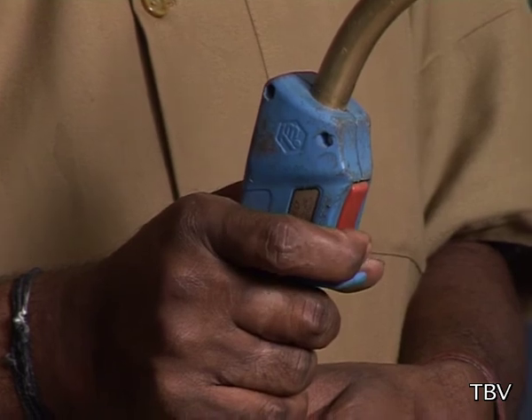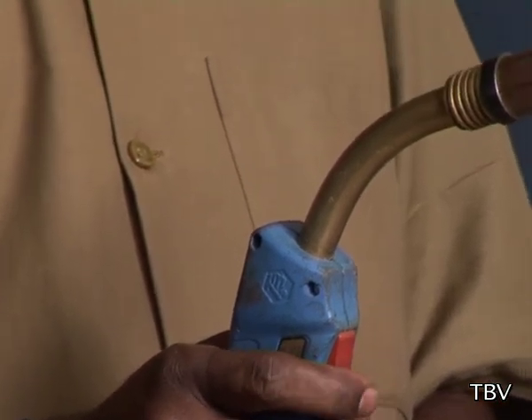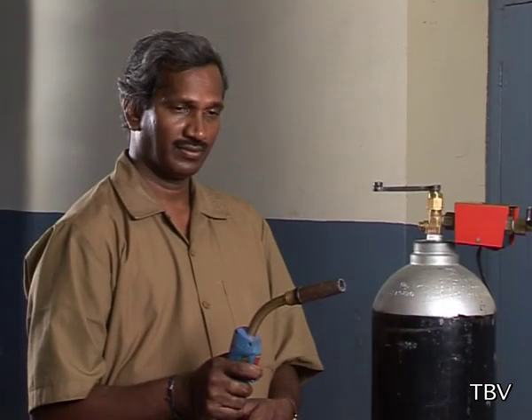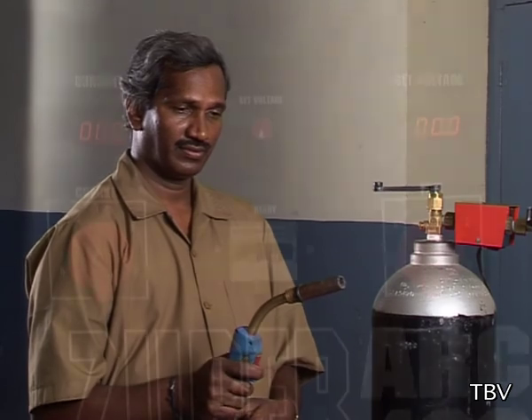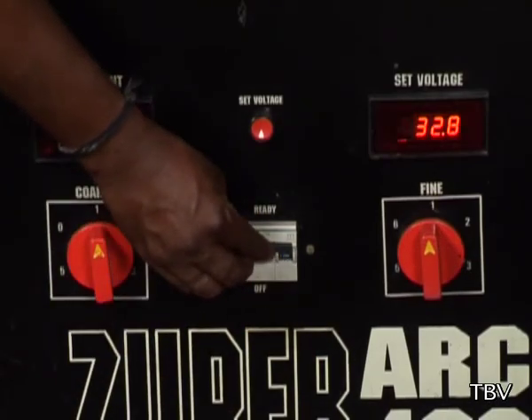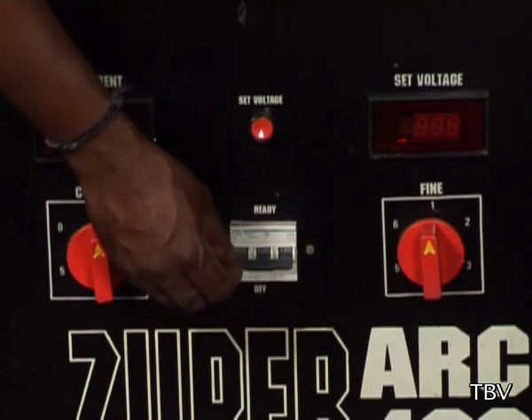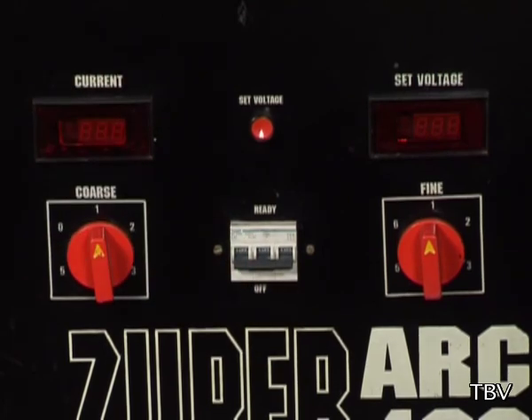Otherwise, once the heater is switched off, the CO2 gas in the heater, flow meter, and the cable turns to liquid form and therefore may damage the equipment and accessories. Let the gas flow out completely by switching on the torch gun. When the gas is used up completely, switch off the welding machine and shut down the power supply.